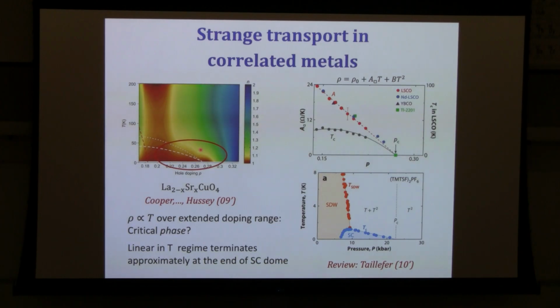Now, interestingly, this phenomenology is actually not special to that cuprate. It's observed in other cuprate materials, and it's even observed in other unconventional superconductors that chemically have nothing to do with the cuprates. They're extremely different. So this is an organic superconductor, which is tuned not by doping but by pressure. Here there's actually a spin density wave or an antiferromagnetic phase, which is suppressed by applying pressure. And then there's an unconventional superconductor, which is suppressed at a critical pressure.